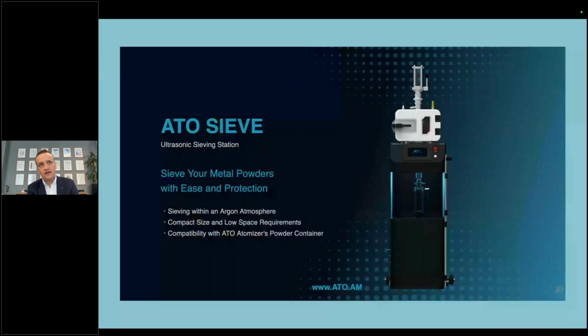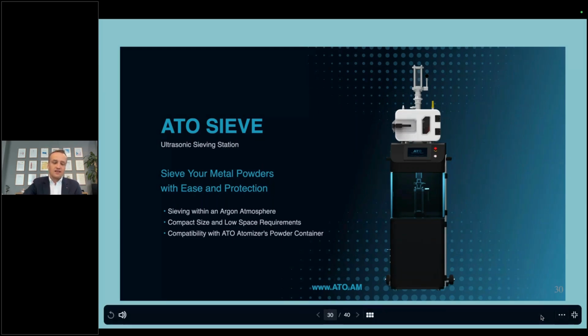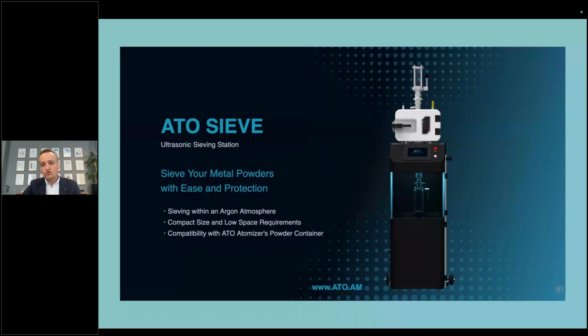It's worth mentioning that whenever you are atomizing the material, it seems to be obvious that you need to sieve the material after the atomization process. To maintain the quality of our powder, we developed our ultrasonic sieving station, which is fully compatible with our ATO container. It means, for example, you can close the valve in your atomizer and put your powder in a safe way under argon atmosphere into your sieving station, and you can sieve your powder also under argon atmosphere. So whenever you need to work with highly reactive material which can oxidize a lot, like magnesium or titanium, you can also work with the ultrasonic sieving station, which can improve the sieving process by avoiding clogging.